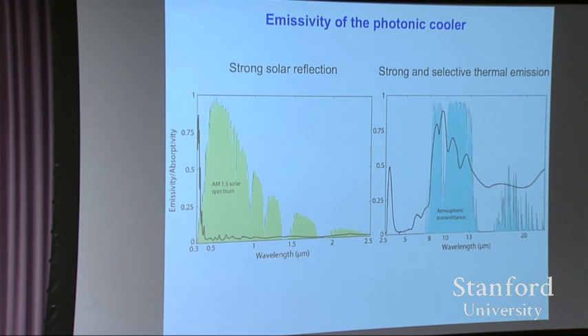With 0.35% per degree C degradation of current photovoltaics, what limits you to not getting, say, 10% efficiency increase? You don't. Well, it's 0.45% relative. So that translates into about, for a 20 percentage point efficient solar cell, about 1 percentage point per 10 degrees.